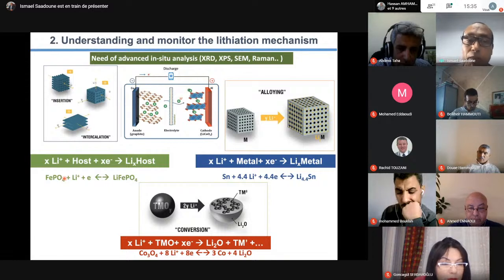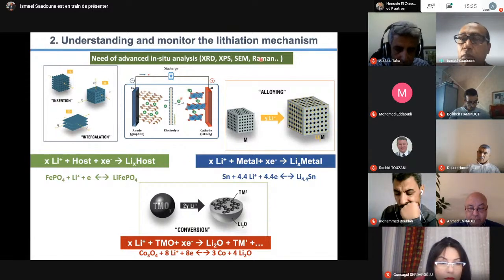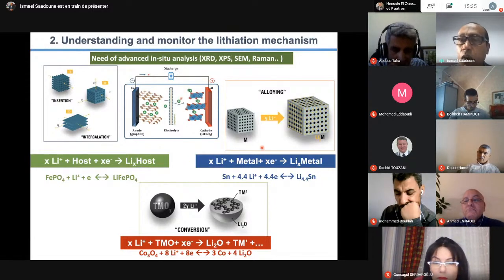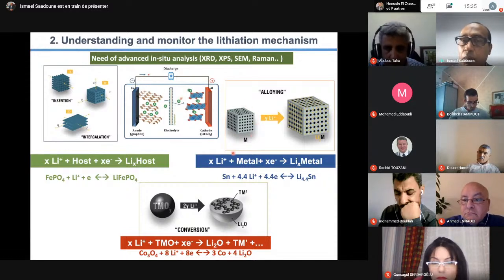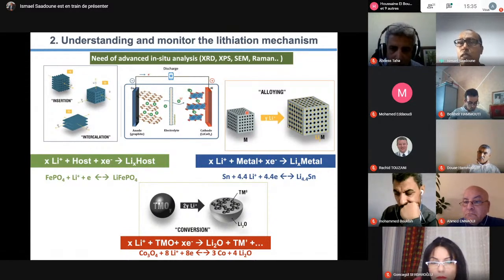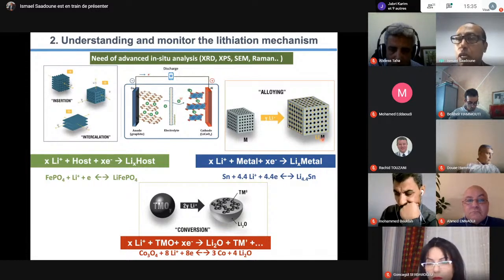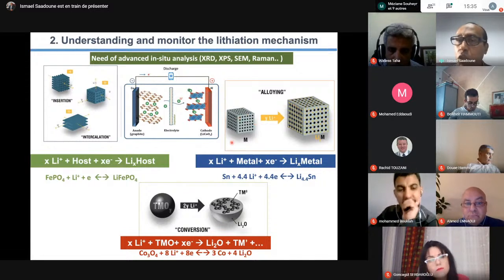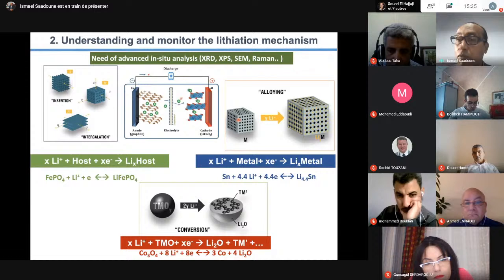This is soft chemistry. We have the second mechanism, what we call alloying. So you have this metal like silicon or antimony as anode materials, and we put lithium and we form some alloy, lithium metal. The problem of this mechanism is that we have huge volume change during charge and discharge. If you have big volume change, you can produce cracks in the particle, and then your performance goes down.